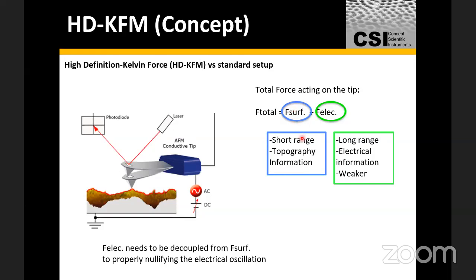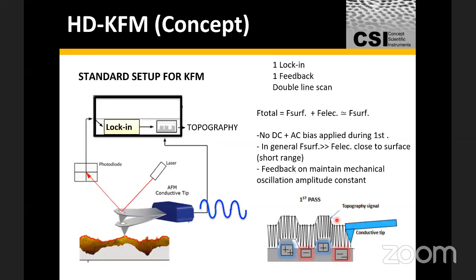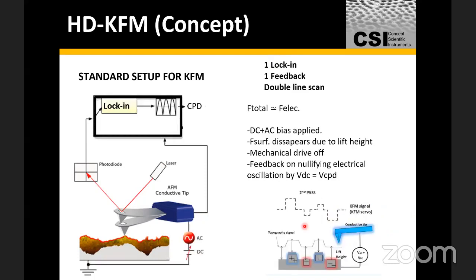Obviously, this problem is compounded with the fact that there's an intrinsic difference in the intensity of these forces. Long-range forces, as we know, by the very virtue of being long range, are much weaker. So being able to capture their signals requires some clever instrumentation that we adopt in scanning probe microscopes these days. Traditionally, the way this has been done is you first measure the topography of the surface. That is, you make the surface measurement, and then you lift the cantilever up a bit and make the second measurement. That is the electrical measurement.